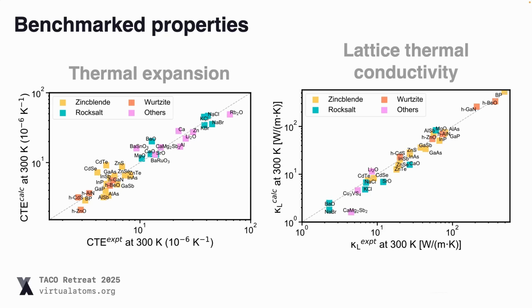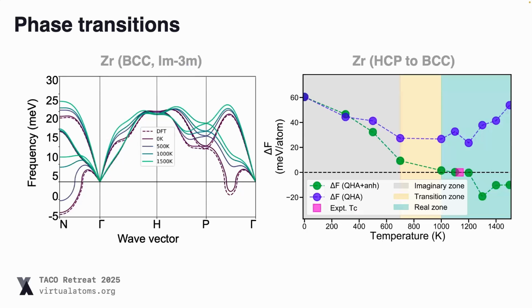This was all done using the PBE exchange correlation functional. So there's a recent paper showing that you can get 10 to 20% difference in your thermal conductivity depending on your exchange correlation functional. But I think it's quite nice, and it's fully automated, and all of this was really done extremely quickly.